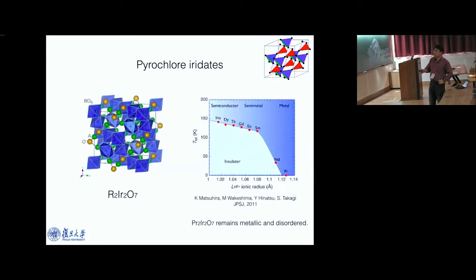So there is a change of this physical property. And almost all of them experience a metal-insulator transition around 120 to 140 Kelvin, with magnetism turning on. So there is a metal-insulator transition with the emergence of magnetism for most of the materials except this one, the praseodymium, which remains metallic, and most of the time it's disordered. So although the system has local moments from the rare earth side, this local moment remains disordered most of the time. And the conducting electrons, which come from the iridium side, remain metallic all the way.